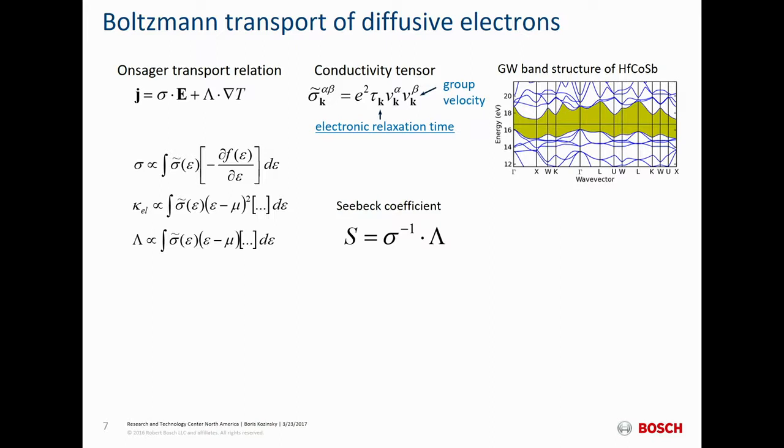And then you can plug in the velocities for the electrons, basically the slopes of the band structure, into this equation for the electronic conductivity, which comes from the Boltzmann transport equation solutions. And you can do the same for the Seebeck coefficient, and then get something just from the band structure for the Seebeck coefficient, because what happens in that case is that the lifetimes of electrons essentially cancel out to first order. They don't cancel out in the electronic thermal conductivity and the electrical conductivity.